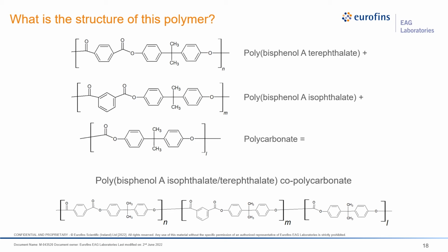So what does the structure of this polymer look like? If we take our BPA terephthalate, our BPA isophthalate, and our polycarbonate, we get the structure that you see at the bottom. So this is our polybisphenol A, isophthalate terephthalate, copolycarbonate. When we connect these, we use the nomenclature N, M, and L to denote the relative ratios or the amounts of these different monomers relative to one another. So we can dig a little bit deeper into the data and determine what this ratio is.